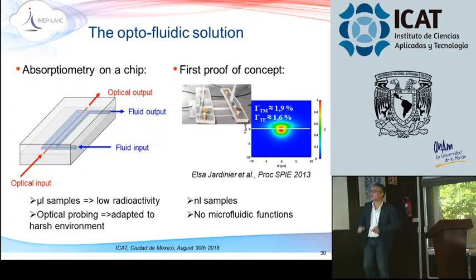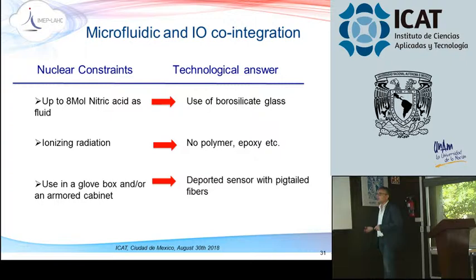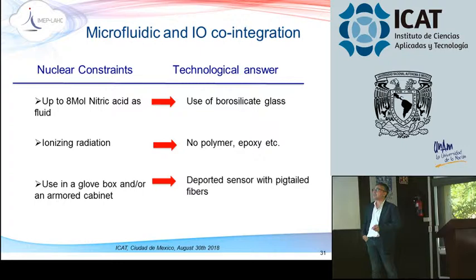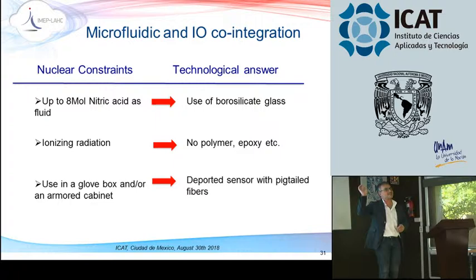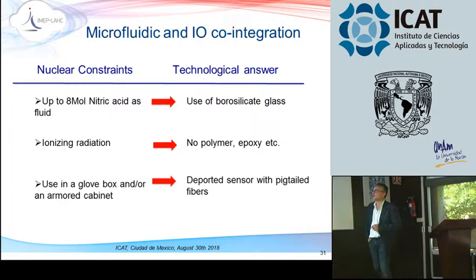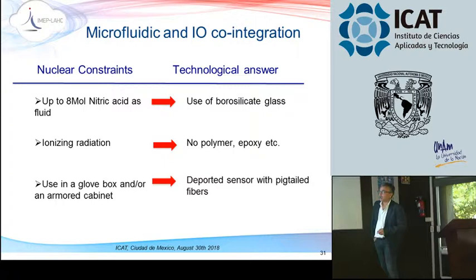So the proof of concept was done, but then we had to go to nuclear plants. So what you have to know is that when you are using nuclear fuel reprocessing, they are dissolved into nitric acid with a concentration of 8 mol. Just for reference, pH 2 is 10 to the minus 2 mol. So you actually have negative pH. So it's really a strong acid, so we have to use a glass that is really strong, which is borosilicate. And then, of course, there are ionizing radioactive elements, so we can't use any glue, any plastic, anything.